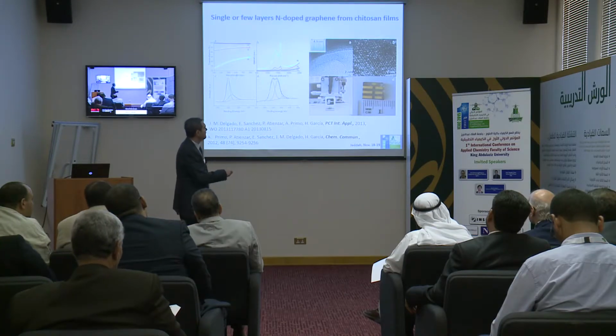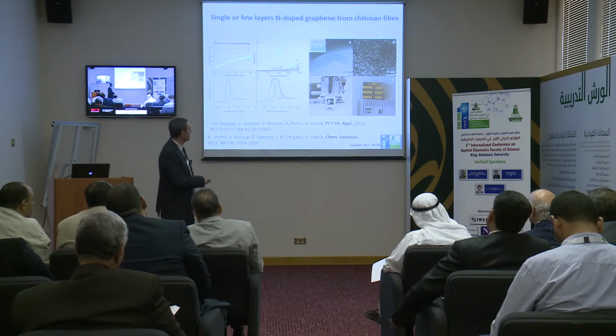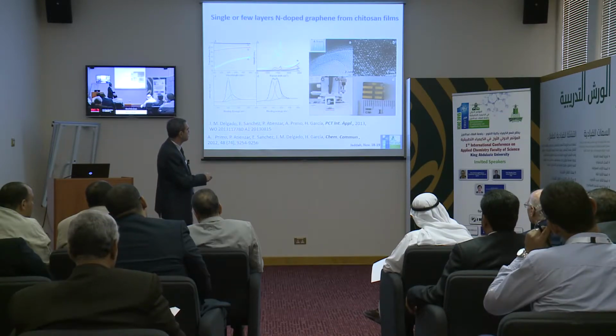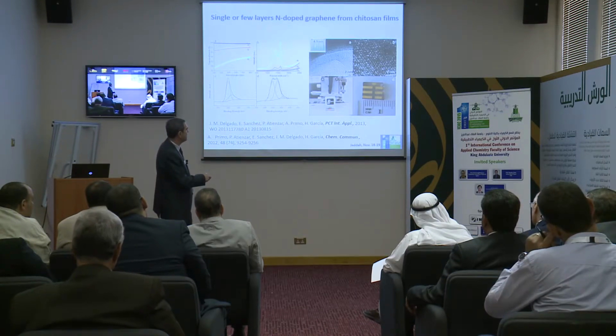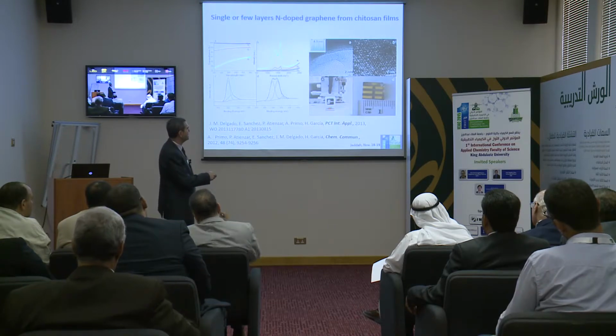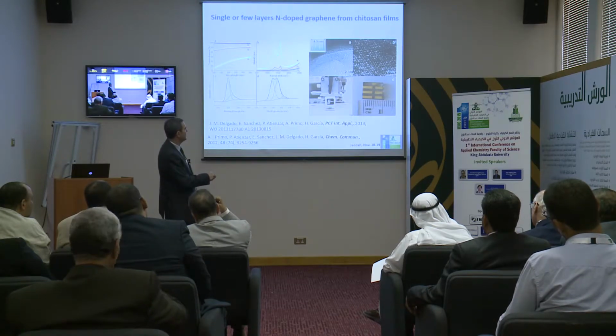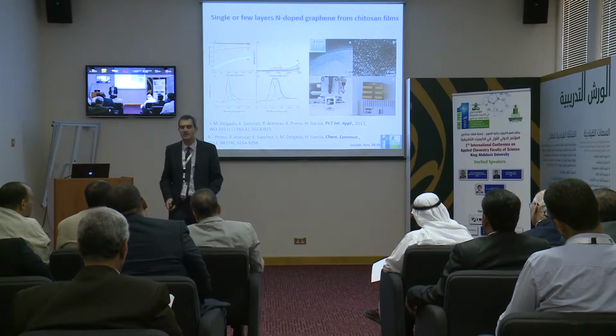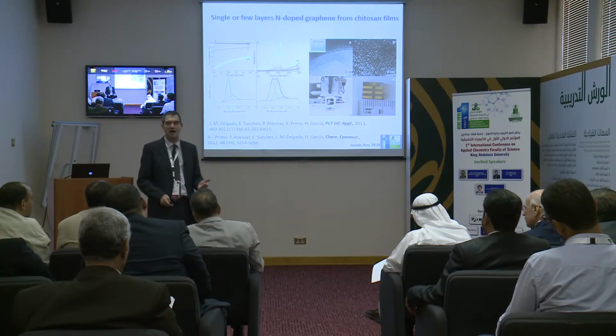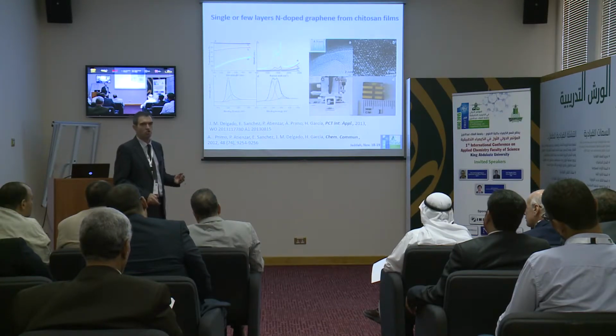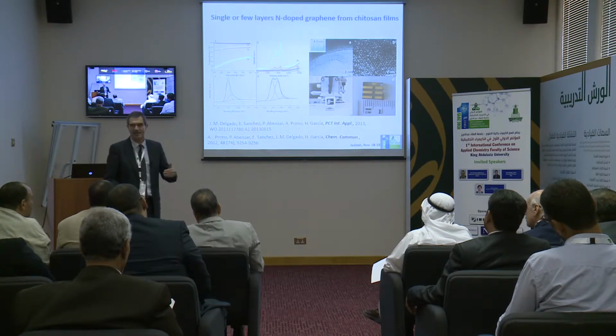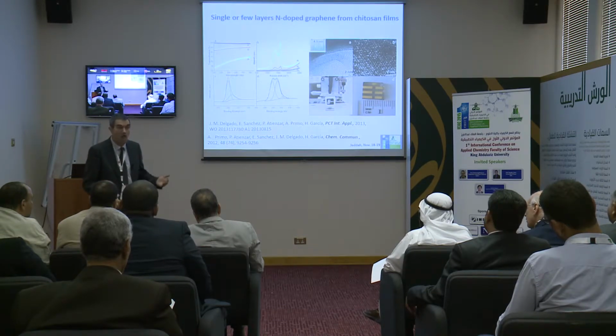Of course, when you have films, you can measure conductivity, and here is the setup that we are using to measure the conductivity. Here is the film, and here we measure the conductivity, and this is the type of cells that we prepare. And the conductivity of our graphene is about 100, 200 ohms squared. So this is not the limit. There are much better graphenes for conductivity than ours, but we should not forget that we want this graphene